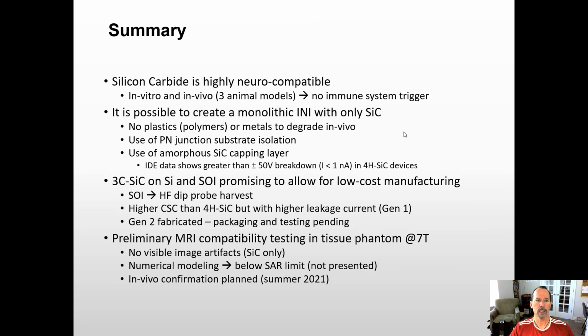So in summary, we have silicon carbide, which is highly compatible with the brain. We believe this from our in vitro and in vivo studies where we saw no immune system trigger occurring. It's possible to create a monolithic INI with only silicon carbide, no plastics or polymers, no metals. We use PN junctions to isolate traces through the substrate, and amorphous silicon carbide as our capping layer. And again, our IDE data showed outstanding performance with leakage current less than a nanoamp, out to plus or minus 50 volts for many of our devices.